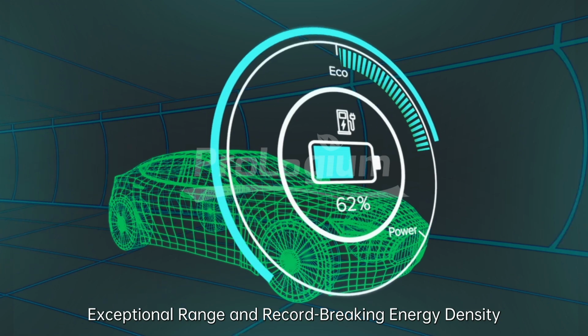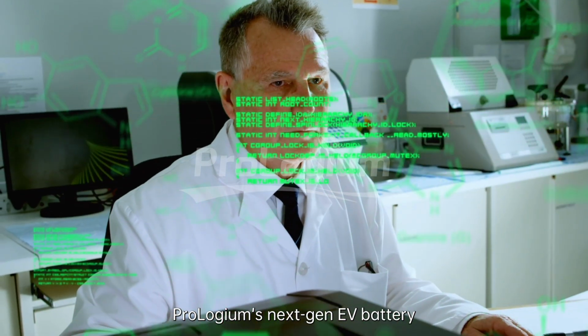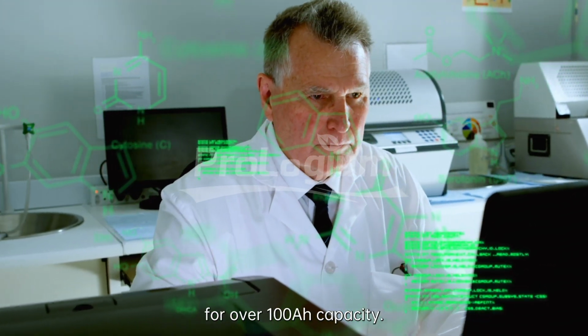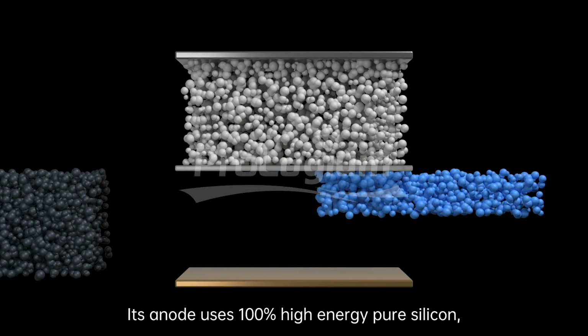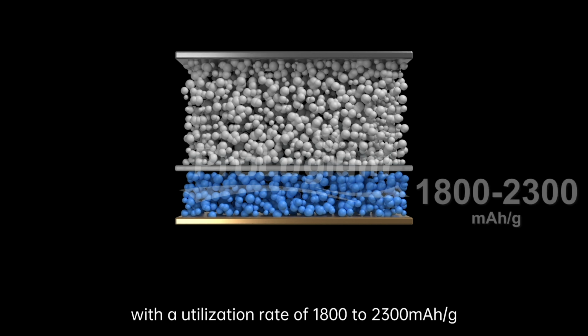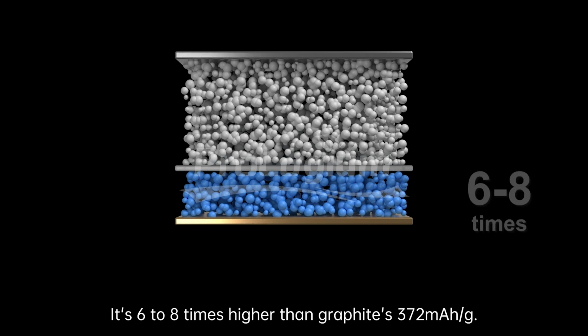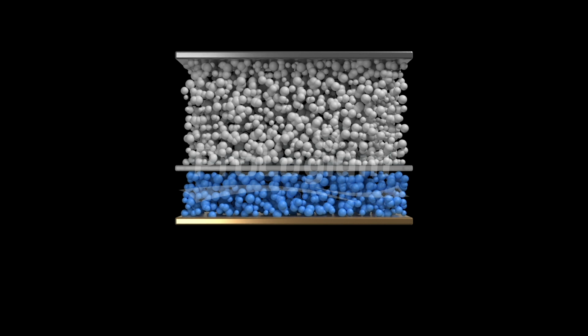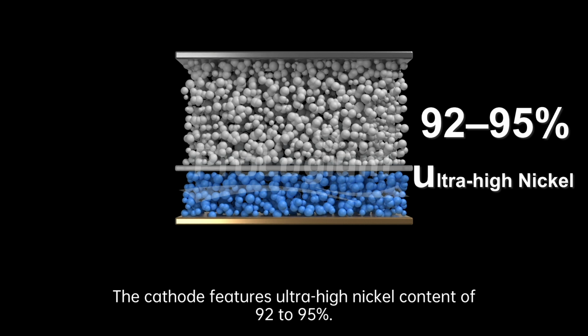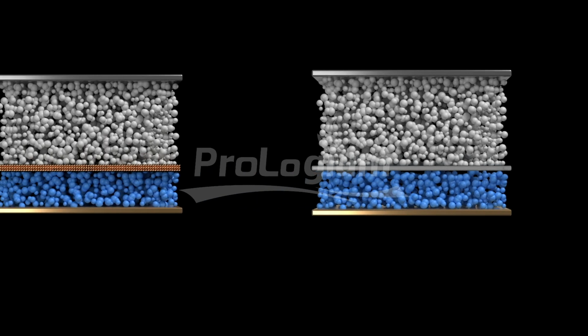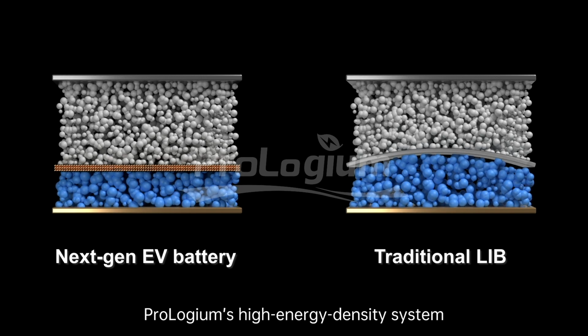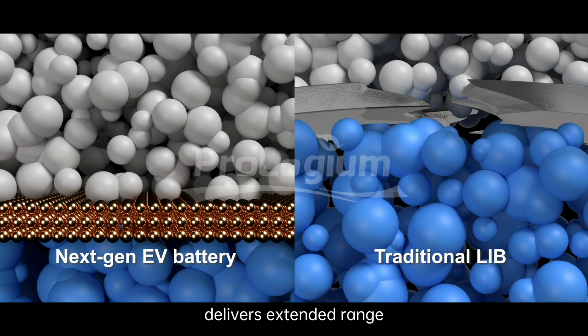Exceptional range and record-breaking energy density. ProLogium's next generation EV battery is the first in the world to be TUV certified for over 100 Ah capacity. Its anode uses 100% high-energy pure silicon with a utilization rate of 1800 to 2300 mAh per gram. It's 6 to 8 times higher than graphite's 372 mAh per gram. The cathode features ultra-high nickel content of 92 to 95%. Unlike conventional lithium-ion batteries, ProLogium's high-energy density system delivers extended range without compromising safety.